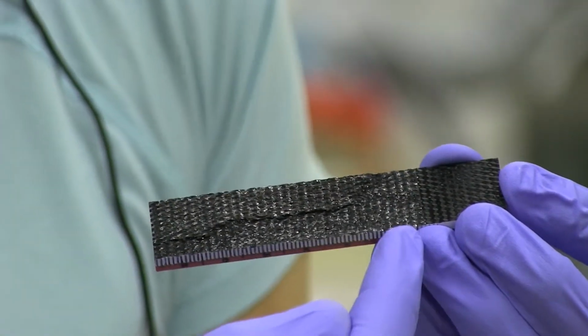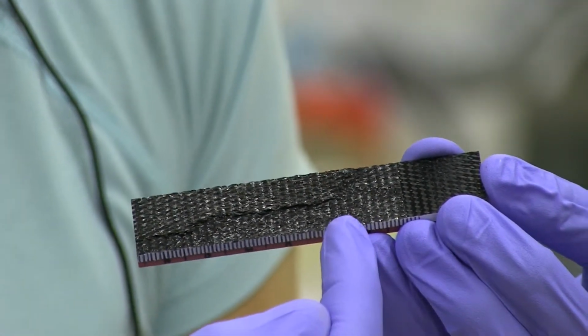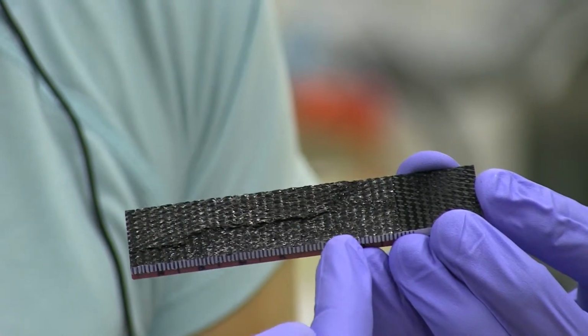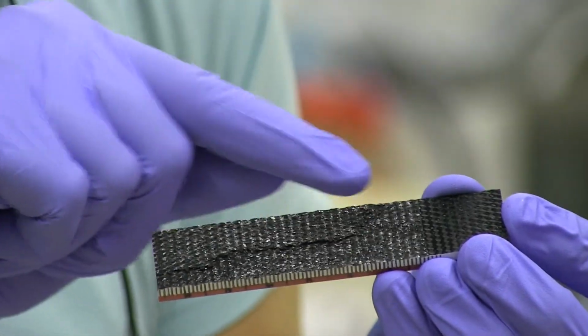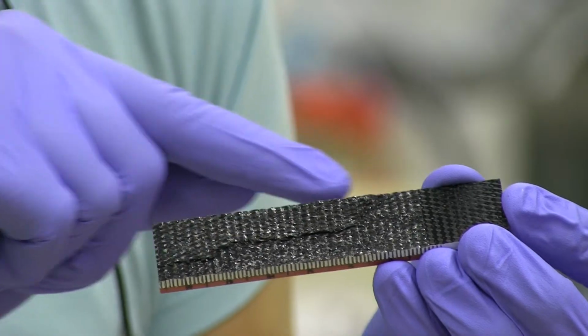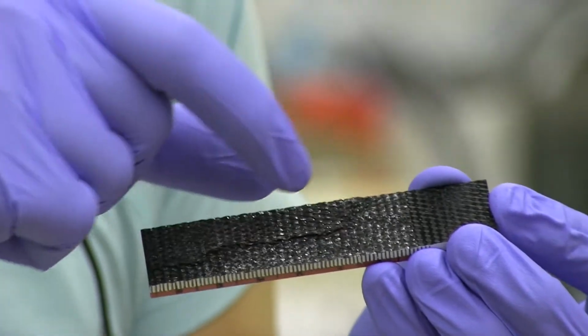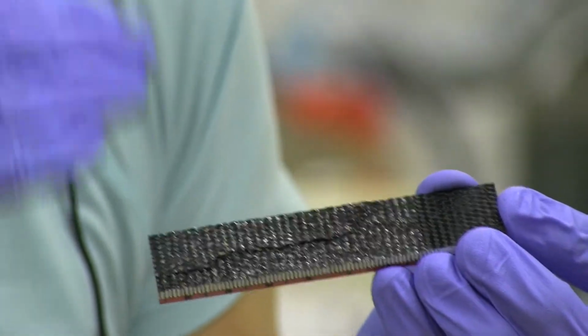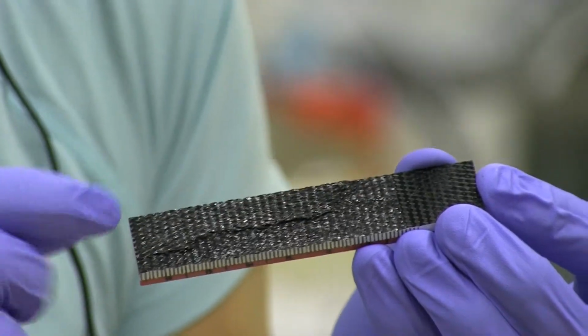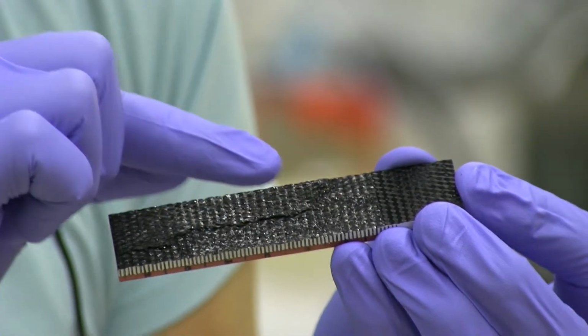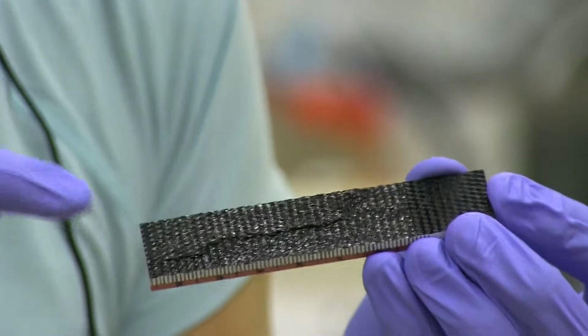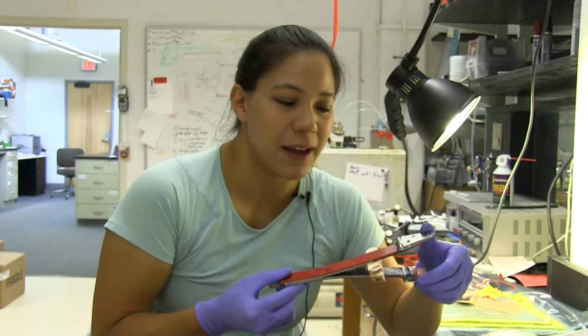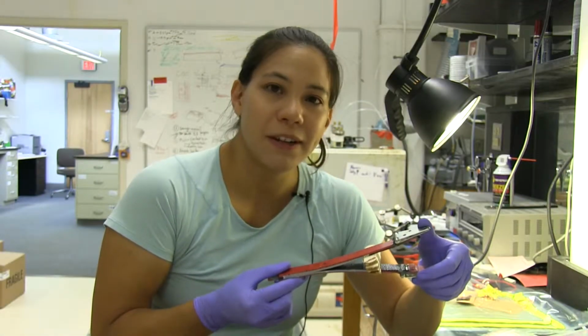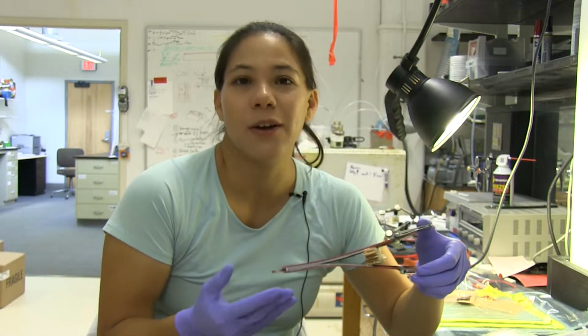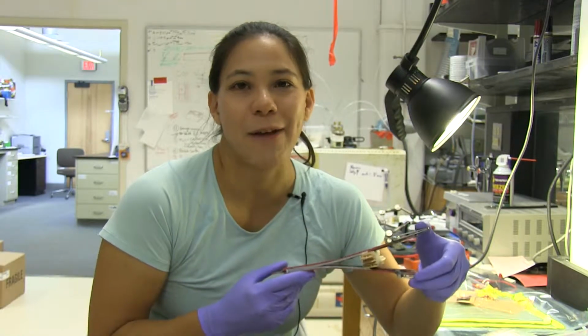You can see here that as the crack was propagating, about 1.5 centimeters in, it started to tear through the next ply up, and so it left behind the layer and tore through half of it, leaving behind the next layer up stuck to the surface below, and so the crack had to tear through the middle of this next ply to propagate at all. We're looking to see how this can improve the reliability of composites and lighten the load and ultimately make a safer aircraft.